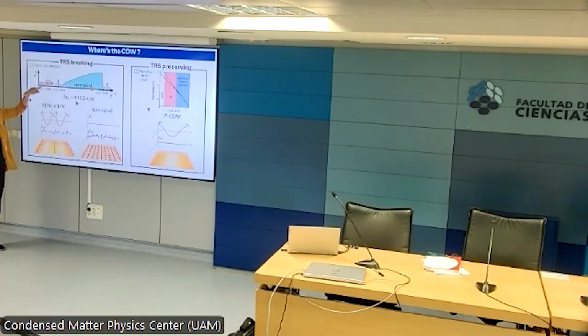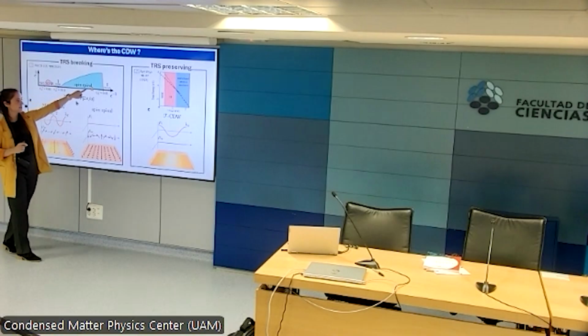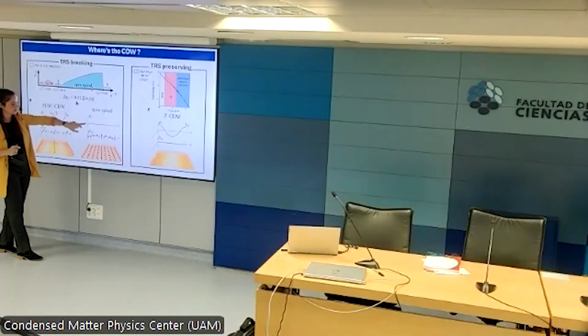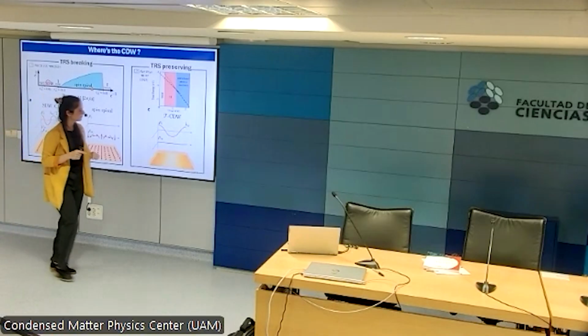You have a spin density wave phase predicted. And in this case, it's not just a spin density wave phase at these epsilons. It's actually a mixture of a spin and charge density wave combined. So you would have a spin density wave with a given periodicity lambda, and then a charge density wave superimposed on it that has half the periodicity. If we keep moving along the interaction line, we have a trivial quantum spin Hall insulator state, and then we end up in this spin spiral state. This spin spiral state has no charge density wave associated, whereas the spins are predicted to precess along the x-axis.